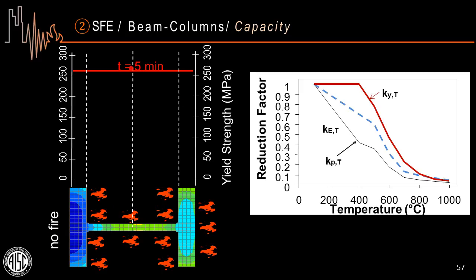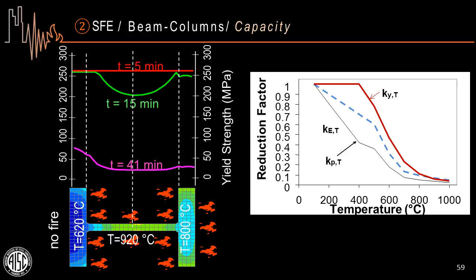Five minutes into the fire, we see that the yield strength of the steel is constant through the depth and has its full capacity at 255 MPa, equivalent to 36 ksi steel. Fifteen minutes into the fire, the web, which is thinner, heats up faster, so it's hotter, and now it has lost some of that yield strength, on the order of 200 MPa. At the time of failure, we see a significant reduction in the yield strength, but we also continue to see a non-uniform distribution of it. Just like at 15 minutes, at 41 minutes the yield strength is no longer constant through the depth of the section.